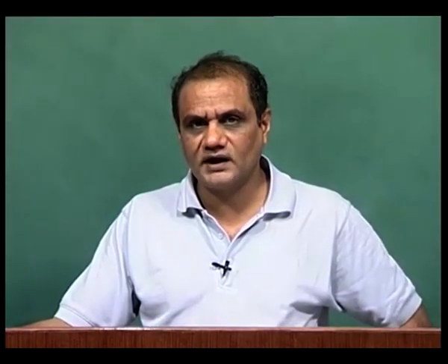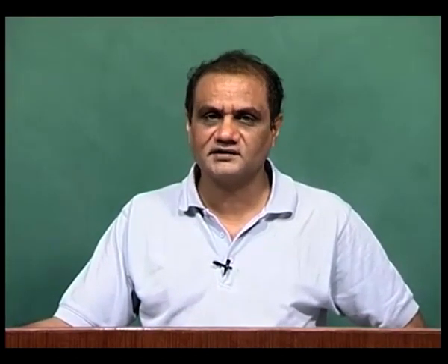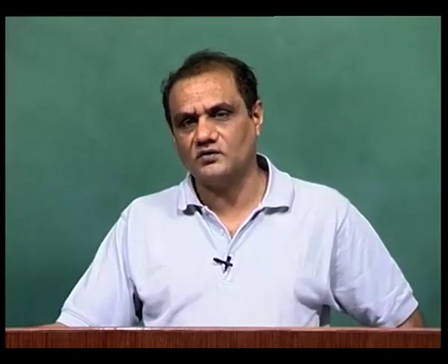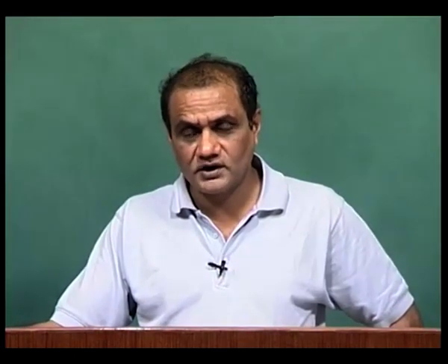First thing which I will show you is that something happens at the Brillouin zone boundary. At the zone boundary, I will show you that the Bragg's diffraction condition gets satisfied, and therefore, the electron wave is strongly reflected at these zone boundaries. So, that is really the purpose. Therefore, it becomes a lot easier to analyze things in the reciprocal space, and this is where the importance of this comes in.